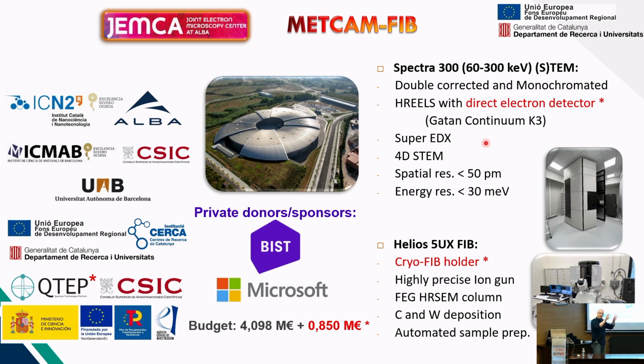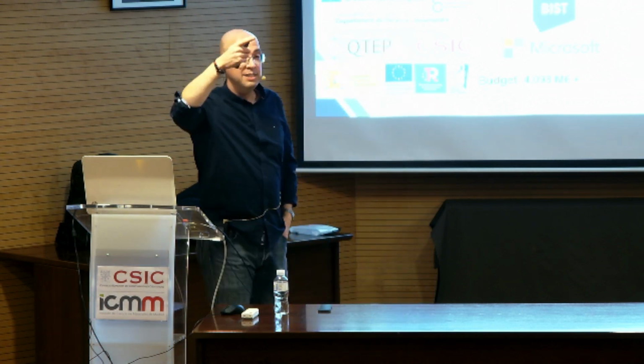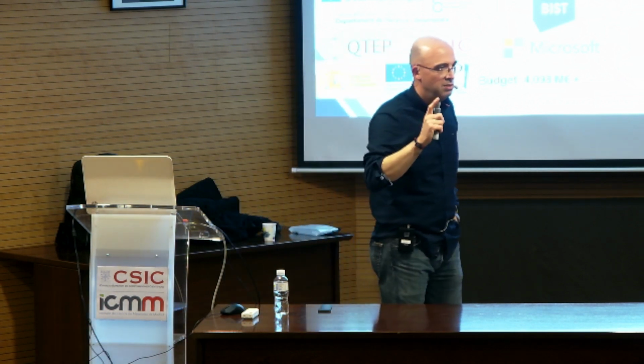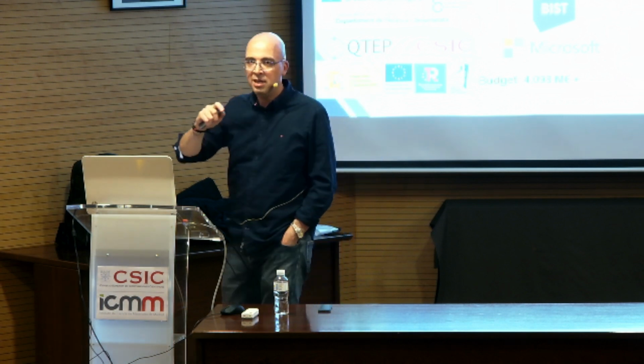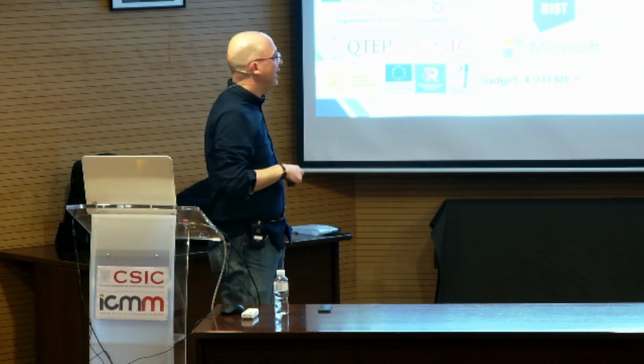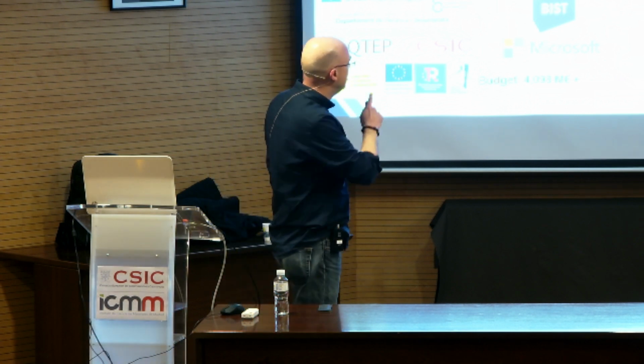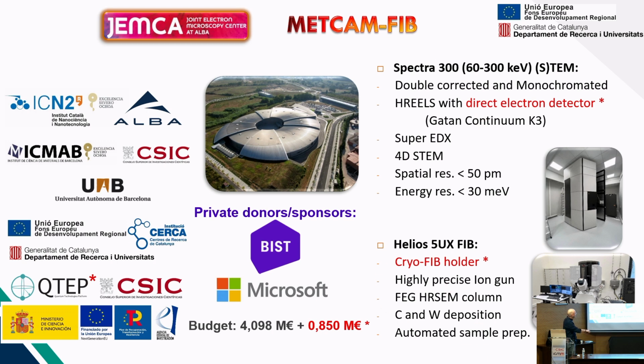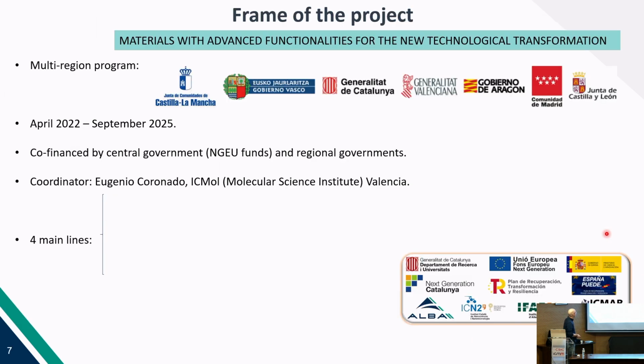Before, you could only see the atomic columns in every material, but now you can even determine the momentum of the electron when it's crossing your sample, even in each atomic column. So you really know which is the deflection of your electron beam when you are crossing a certain atom or a certain column of atoms. And then what you can do is measure the electric field or the magnetic field of the atoms around. For example, in Complutense, there is Gabriel Sánchez Santolino. I don't know if you know about him. He has many works about this for STEM in order to calculate magnetic fields and electric fields at atomic scale. So it's really, really nice what you can do with these machines. And then this Helios that is for the sample preparation. So this is all placed in ALBA.